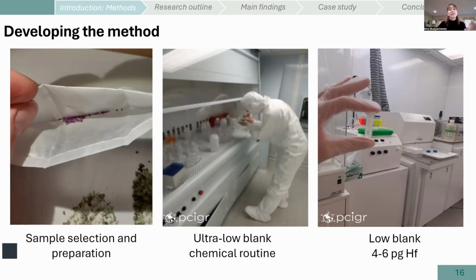That entire process of picking the sample, preparing it, measuring, and getting the isochron for one data point, if I work back to back, takes approximately 2 weeks. The problem is, since we have a step of adding a spike solution before working in the lab, it means that we do a little bit of guesswork with the concentrations. Because of that, I don't process all of the sample at once, since before processing it, I don't know the concentration of all the elements. So to get a robust, statistically good isochron, we need to have at least 3, 4, better 5 data points, and each one of them is a separate aliquot that gets processed consecutively.